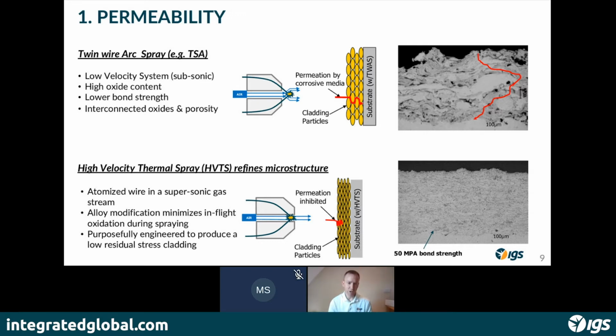And what that meant is we strip off smaller particulates, and more importantly, that they hit the surface with greater energy. So when they hit the surface, they flatten, or pancake, as we like to call it, and create this extremely dense interconnected structure. So as long as we've built sufficient thickness and we have enough layers of the particles on the surface, then we eliminate any potential pathway through to the substrate. So if we have the right alloy selection and we use a high velocity process, we can create this inert